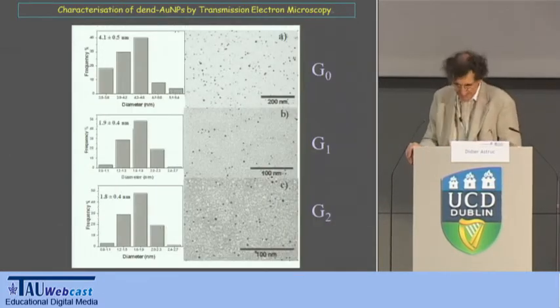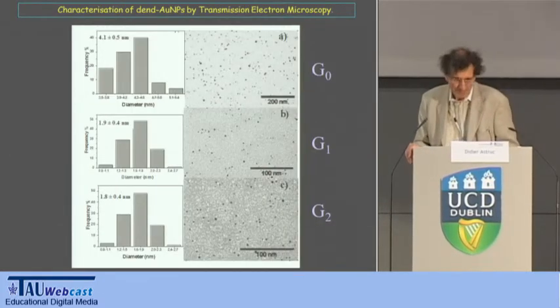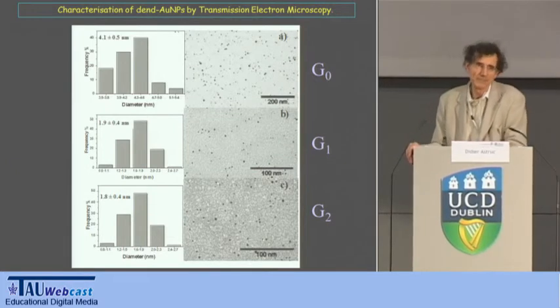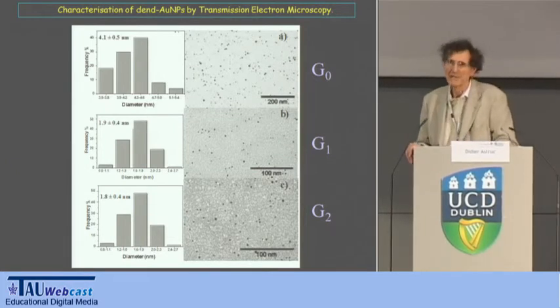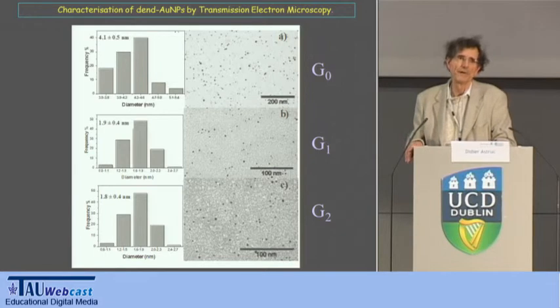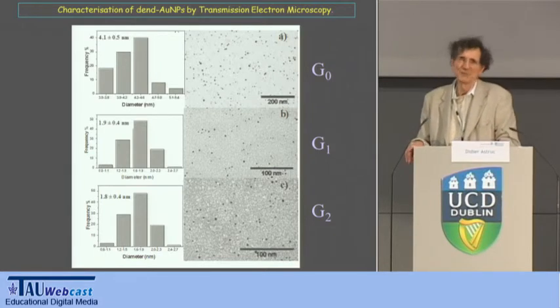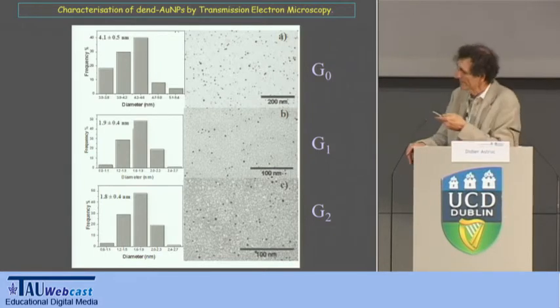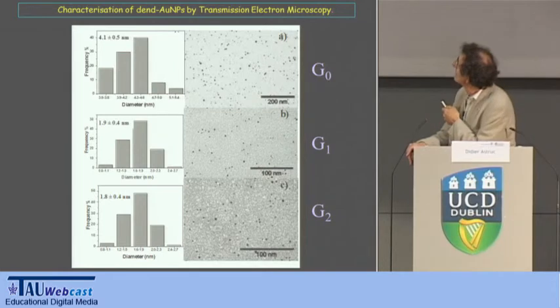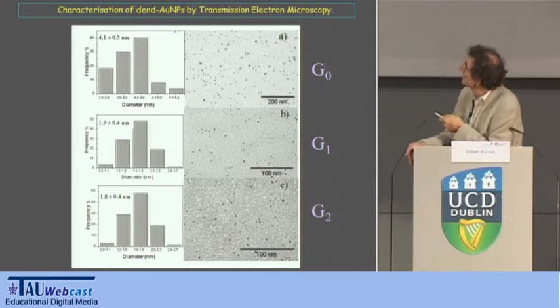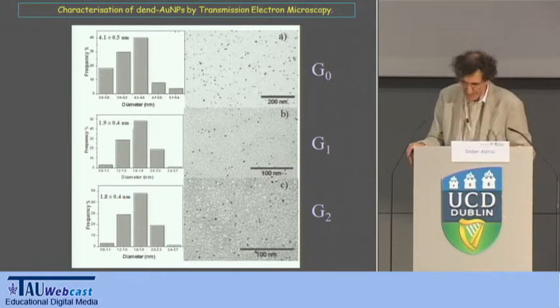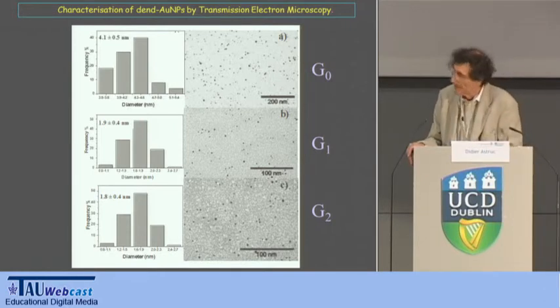And this can be checked by transmission electron microscopy, TEM, or high resolution TEM, which is a major tool for nanochemists to characterize the nanoparticle. And you can see here that the dendrimer of 0th generation encapsulates large nanoparticle, 4 nanometers, and that the first and second generation encapsulate small nanoparticle of 1.9 and 1.8 nanometers.